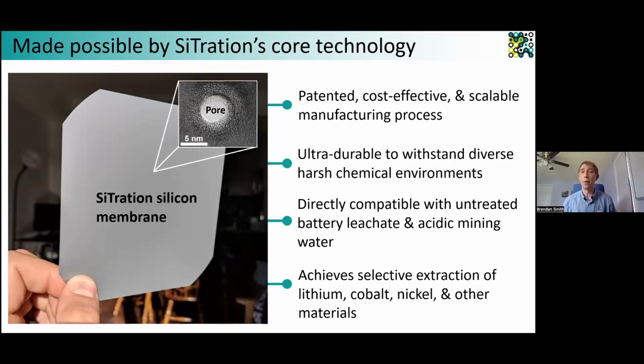So the top three things which are most unique and differentiated and valuable about this technology, number one, we have an extreme amount of tunability with this pore diameter. So anywhere from 5 nanometer diameter all the way up to say 5 or 10 microns, approaching the diameter of a human hair. And anything in between, we can tune the pore size and structure to meet those requirements. Secondly, we have an ultra durable material.